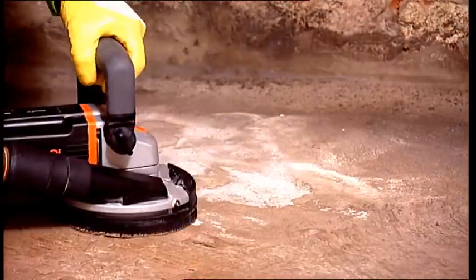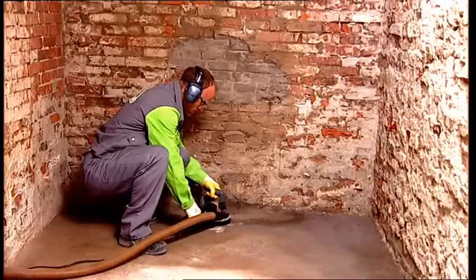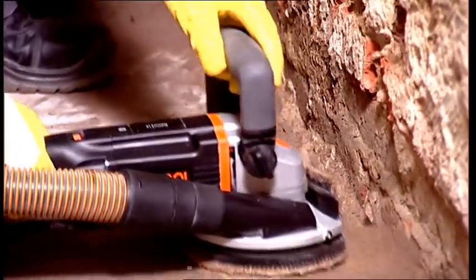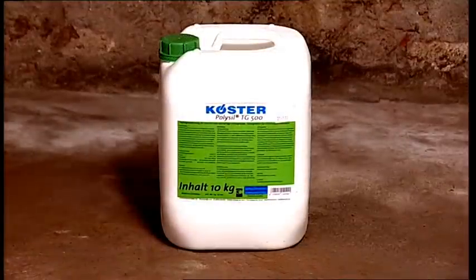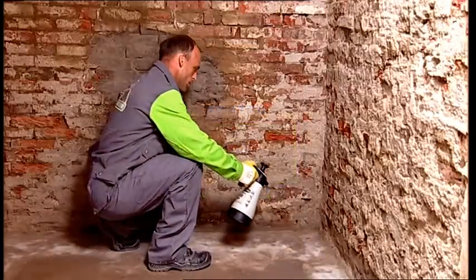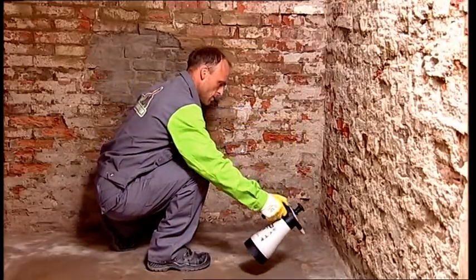Adhesion-reducing coatings on the floor such as paints have to be removed and smooth surfaces roughened to achieve an optimal adhesion to the mineral substrate. Absorptive or salt-contaminated substrates must be primed with Remmers Kiesol TG500, which solidifies the masonry and locks in the salts.